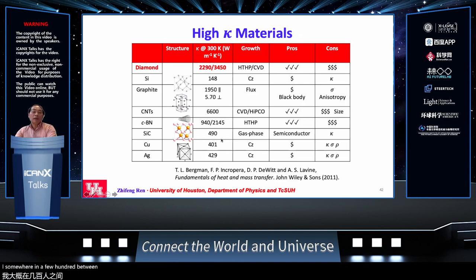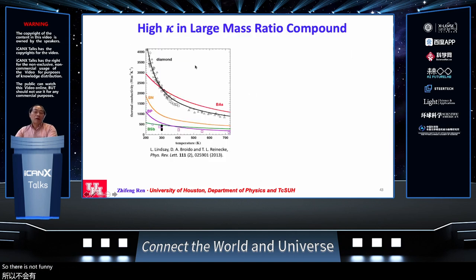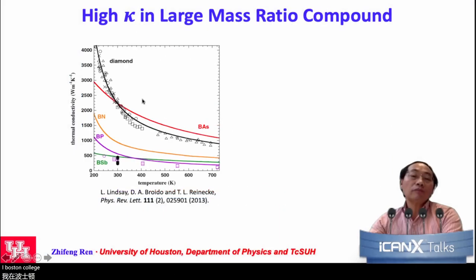Between diamond and those isotropic materials, there is a huge gap, between 500 and over 2000. So is it possible we can discover other materials with high thermal conductivity? Very luckily, my former colleague, Professor David Broido at Boston College, predicted early on that boron arsenide could have thermal conductivity as high as diamond above room temperature. And a few other materials, like boron phosphide, also have thermal conductivity that's not too bad.